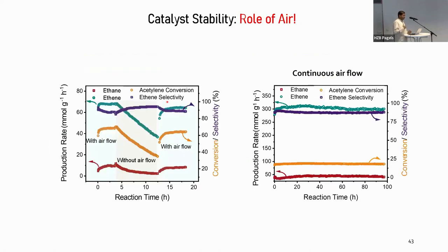Another interesting thing that we observe is that whenever we do the hydrogenation reaction, we make sure that there is no oxygen, right? Because otherwise, how can you do a hydrogenation reaction in presence of oxygen? Here in our system, we realize that if there is no oxygen, my catalyst dies in 1 or 2 hours. Look at this data. Without the airflow, one can look at the ethene productivity, starting from here, and within 5 hours, activity goes down, a dramatic decrease. However, as soon as we add the airflow during the hydrogenation, a very small amount, 5%, activity comes back.